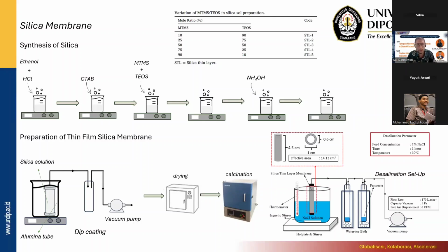I make it hydrophobic using what we call a hydrophobic agent, and in this case I used MTMS, methyltrimethoxysilane. Usually, for silica research, most people use TEOS, tetraethyl orthosilicate, as the main material. But the problem with TEOS is that it produces silica with an Si-OH structure, and the OH groups can easily interact with water.